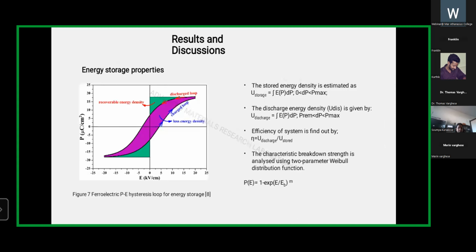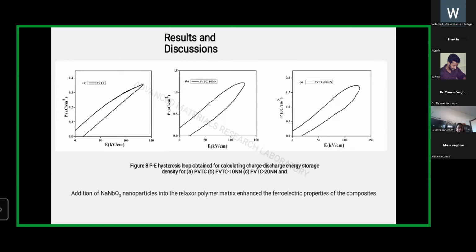And coming to our main storage related studies, the energy storage related studies were done using ferroelectric P-E hysteresis loop studies. And from the loop, it is clear that the green portion of the graph is used for recovering energy density, and the pink portion is the loss energy density. And for exactly calculating the discharge energy density, we have to integrate E dP from the limit P remanence to P maximum. And this is the result that is obtained for the pure polymer and with 10 loadings of sodium niobate and 20 loadings of sodium niobate.